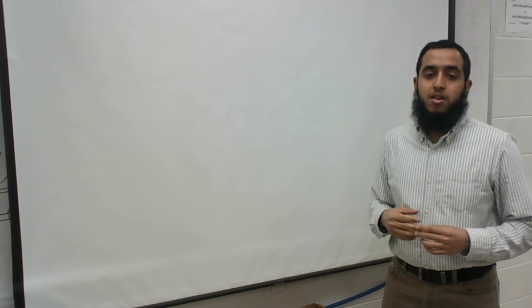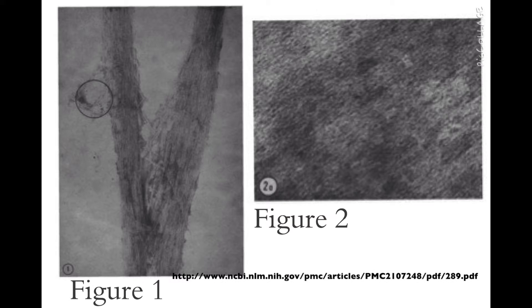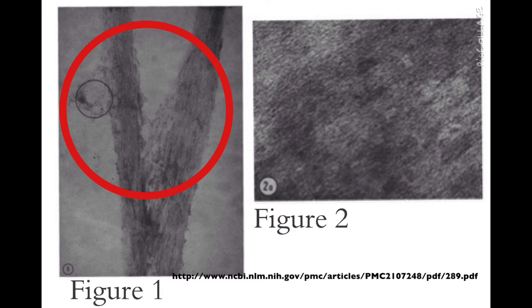With micro-fibrils of such small dimensions, the interpretation of the appearance in cross-section is complicated by the possibility that the plane of the section is not accurately normal to the axis. The packing of the micro-fibrils appears to be irregular, apart from a marked tendency for the planes of the ribbons to lie parallel. This explains how it is possible to obtain fragments of the type shown in figure 1, in which the majority of the ribbons present their narrow aspect to the electron beam.